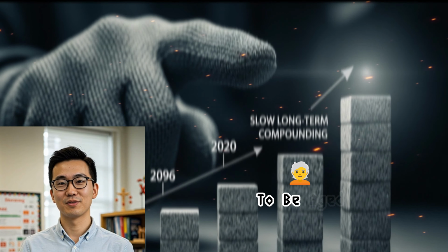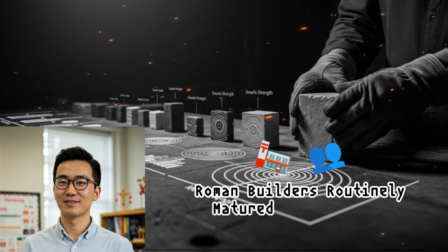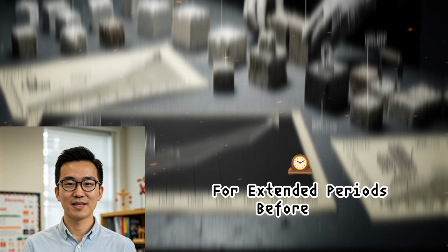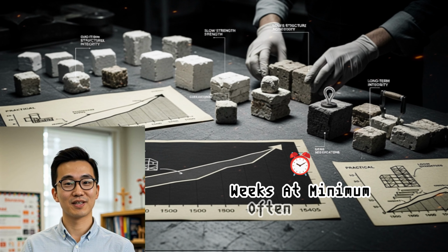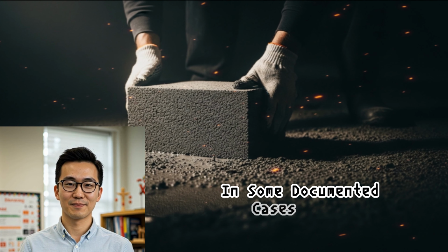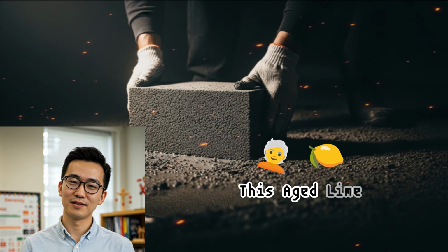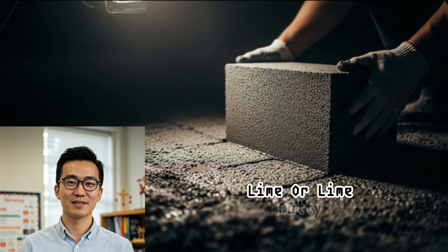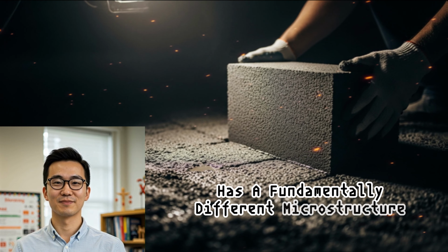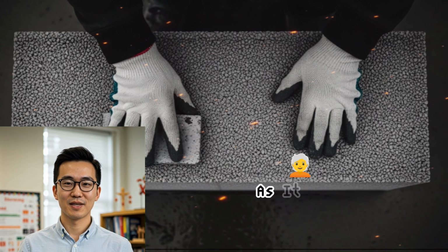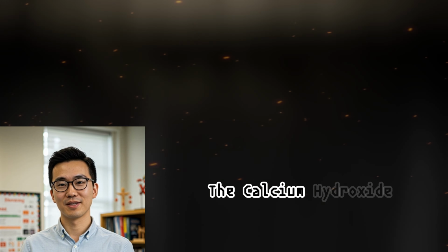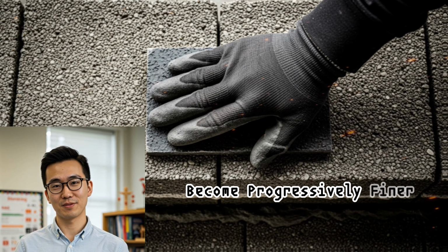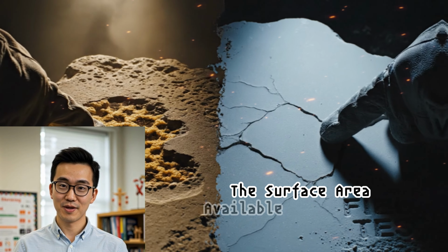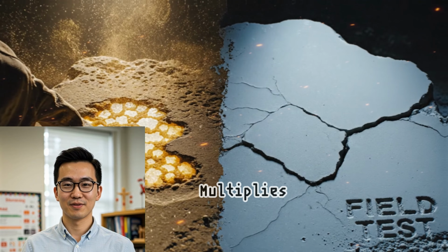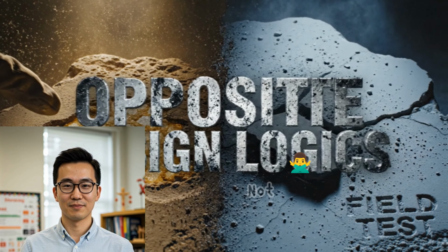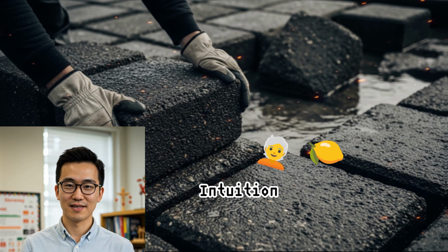The lime has to be aged. Roman builders routinely matured their slaked lime for extended periods before use. Weeks at minimum, often months, in some documented cases, years. This aged lime, sometimes called fat lime or lime putty, has a fundamentally different microstructure from freshly slaked quicklime. As it ages in contact with water, the calcium hydroxide particles become progressively finer and more uniform. The surface area available for chemical reaction multiplies. The material becomes more reactive, not less, the opposite of what intuition suggests.